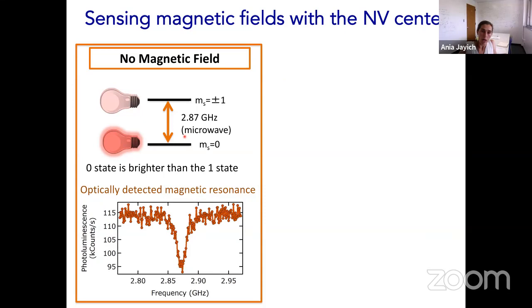And because of the spin-dependent fluorescence, we can optically detect which state the spin is in, because the 0 state turns out to be brighter than the 1 state. I won't go into the details of this, but for now, let's just say the 0 state is brighter than the 1 state. Okay. At 0 magnetic field, this means that if we simultaneously apply a green laser to excite